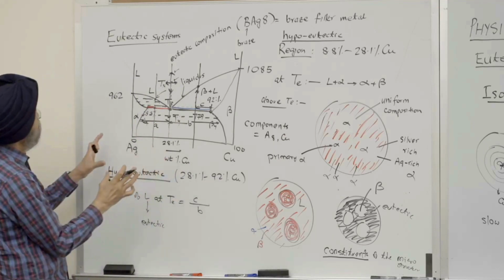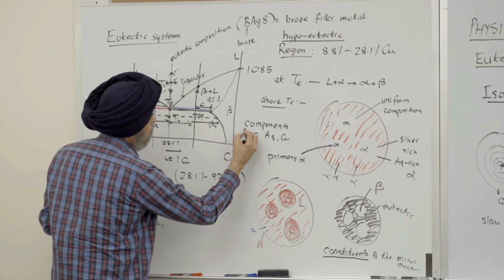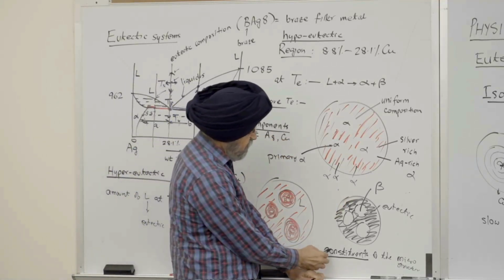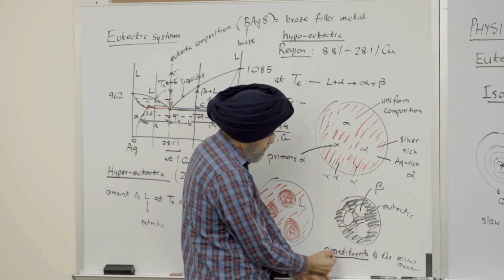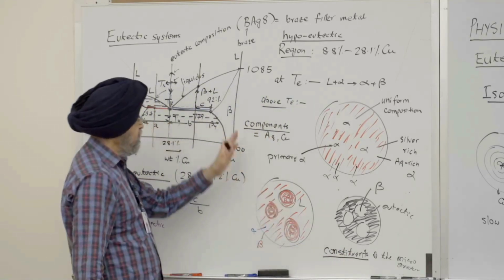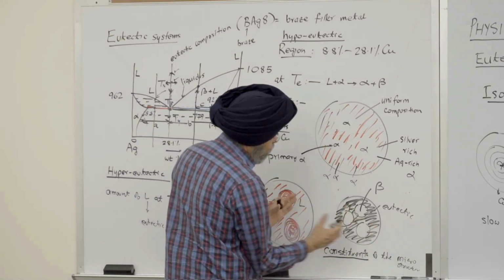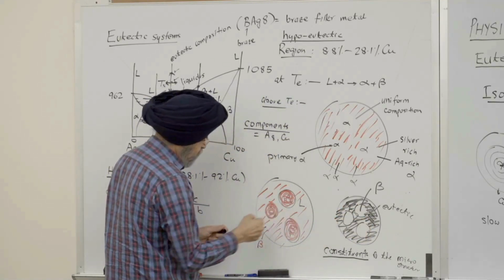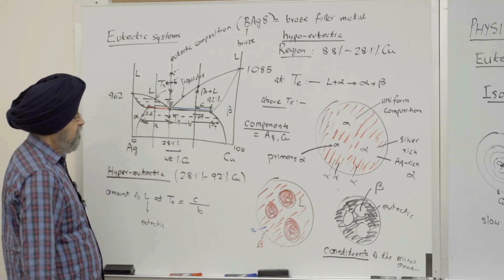This eutectic system has two components, silver and copper. And this microstructure has two features you can see, and we call them constituents. So we have to keep in mind what is a constituent and what is a component. And of course, if we take this microstructure and expand it, we realize that this darkish region is actually eutectic of silver and copper.